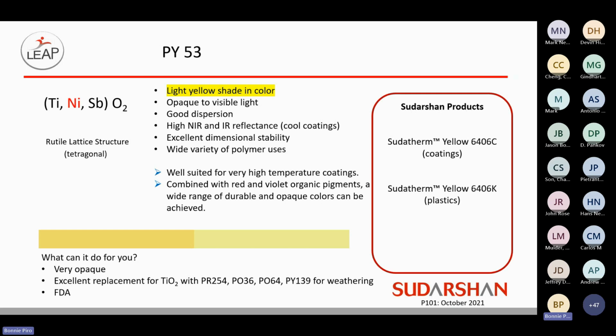Yellow 53 is the greenest in the rutile lattice structure collection of pigments. It's a light yellow in color. Being inorganic, it's very opaque to visible light. It's very well suited for high temperature coatings. And then a good use for this is to combine it with the red and violet pigments that I spoke about earlier, the organic pigments. That opens up a wider range of durable and opaque colors. It's FDA approved or compliant so that we can use it in a lot of different applications. And as I mentioned in many of the slides earlier, it is a great option for replacing some or all of the TiO2 to be able to improve weatherability.